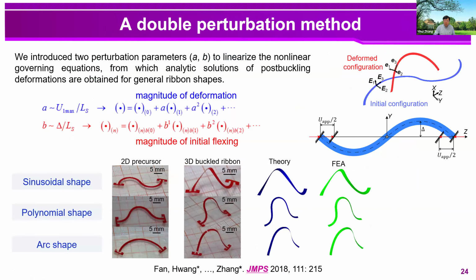And if you want to further predict the 3D configuration resulting from the 3D assembly, we need to have a predictive post-buckling model. And for this purpose, we have developed a double perturbation method for the post-buckling analysis. In particular, we introduced two perturbation parameters to linearize the nonlinear governing equation. And by doing so, we can obtain analytical solutions of post-buckling deformations and also curvatures for general curved beams.